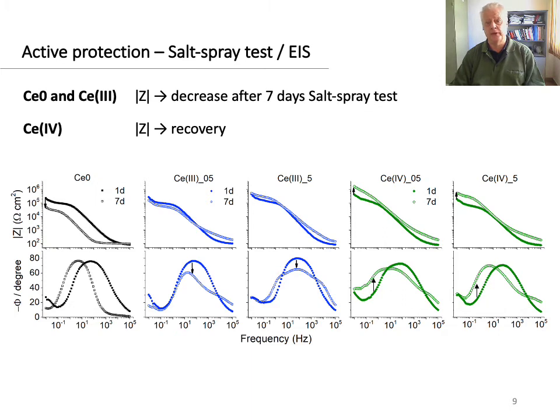More rigorous tests on the self-healing ability were conducted by salt spray tests during 7 days on artificially scratched coatings. Now, the EIS plots were recorded after 1 and 7 days of tests, and the results show that the reference coating presented a drop of the impedance modulus due to the corrosion reactions on the surface. The Ce(III) samples presented a similar impedance response after 1 week of testing, showing, however, no inhibition effect with increasing concentration. On the other hand, in cerium-4 containing coatings, a self-healing effect can be clearly observed, demonstrating here the inhibitory effect of cerium-4 in large defect areas.